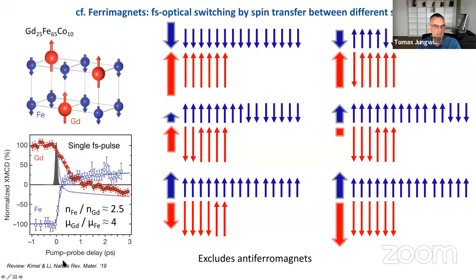And as of recently, when we look at this recent review article on all optical ultra-fast switching in magnets, it's been realized that there's only one mechanism that allows for switching by ultra-short single femtosecond pulse, and the mechanism works in ferrimagnets. It's very important to have two sublattices with different size of the magnetic moments and also different number of these moments present in the lattice. So let's quickly go through the basics of this mechanism. It's based on the conservation of angular momentum.